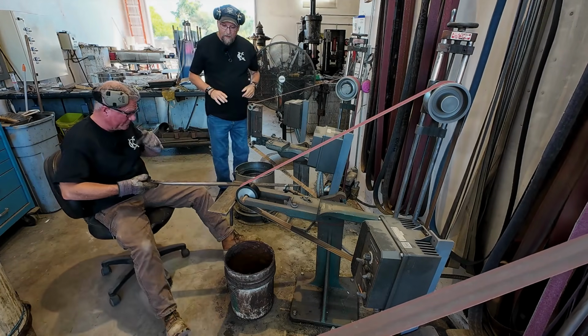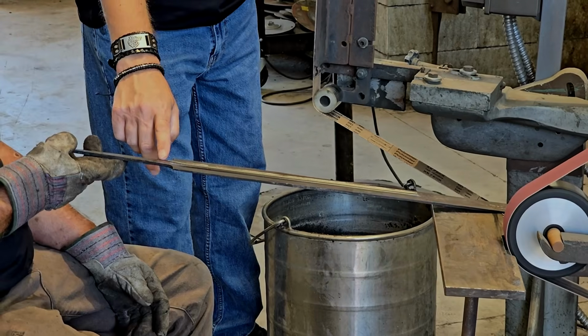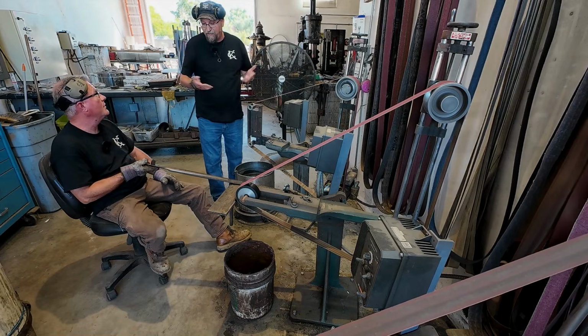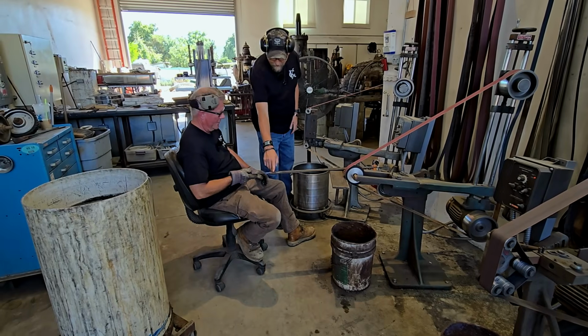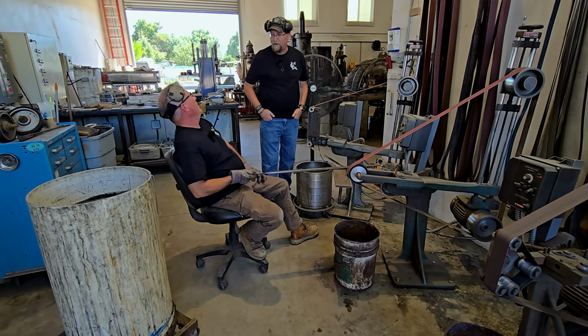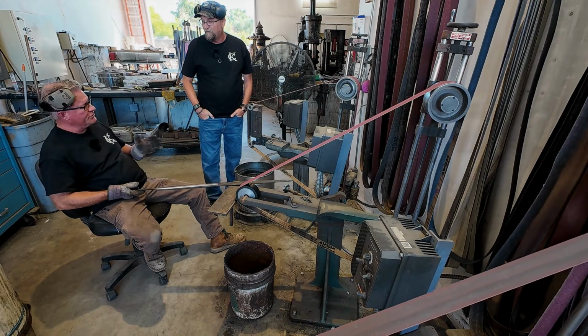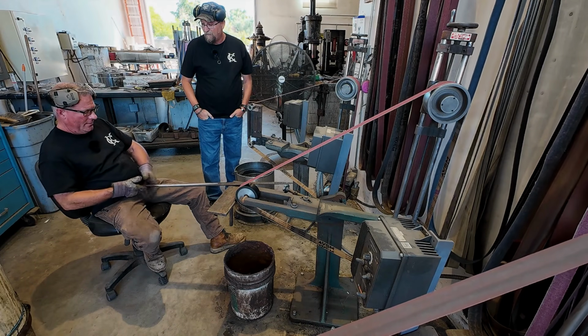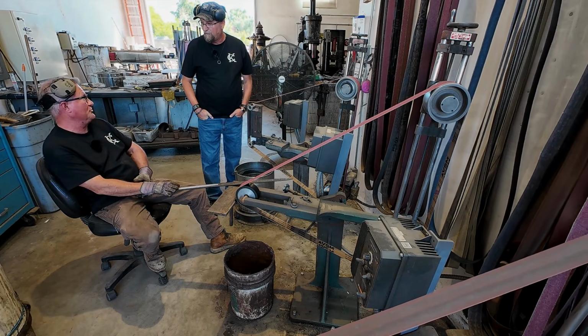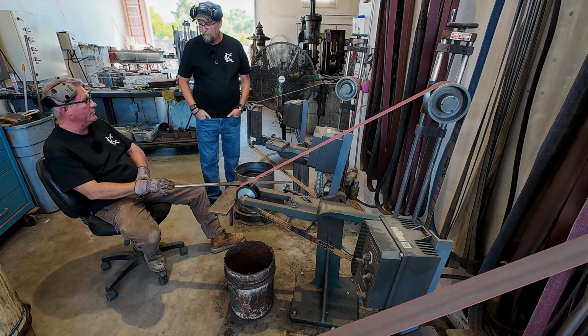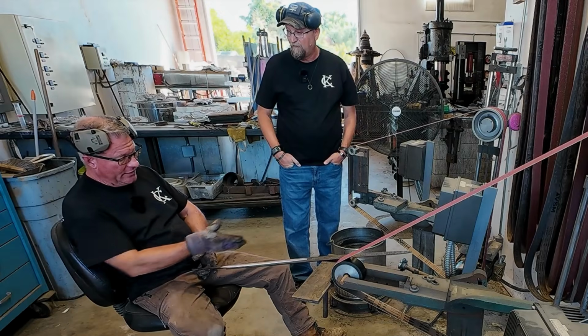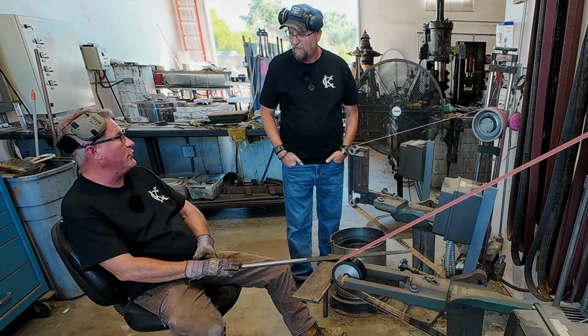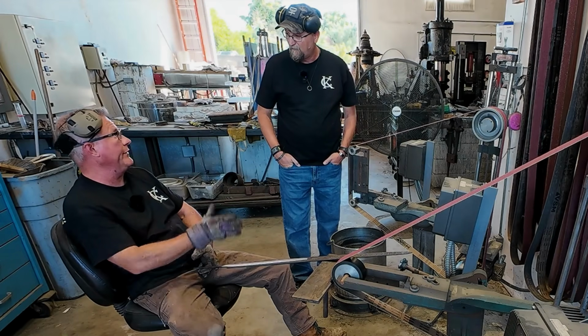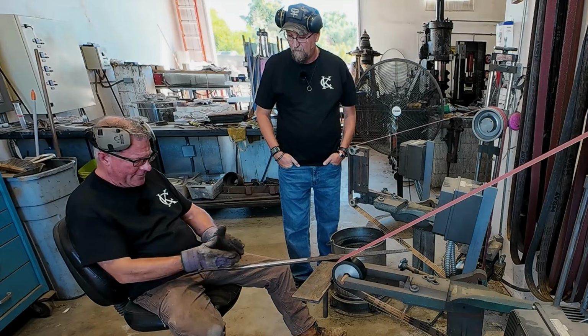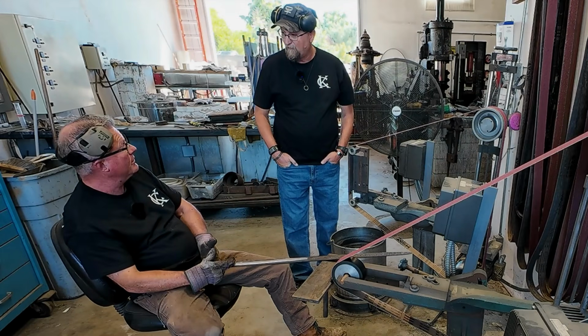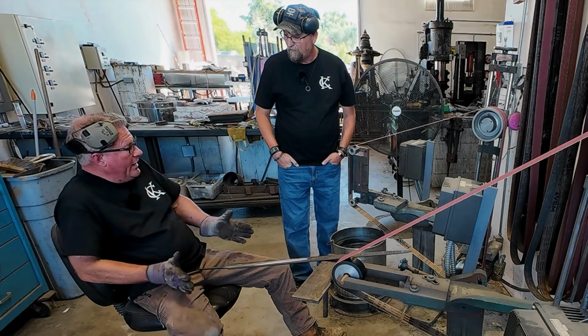I noticed your fuller is going all the way into the tang. Yes. I'm used to seeing in movies and TV that the fuller stops before the guard. So how come you're grinding back into the tang? Traditionally, material was expensive, labor was cheap. So sword steel was a very precious commodity. They forged that fuller in. This one's actually rough forged in. They probably did it even cleaner than I did it here. But they would forge that. If you stop early, well, you can't widen anything out.